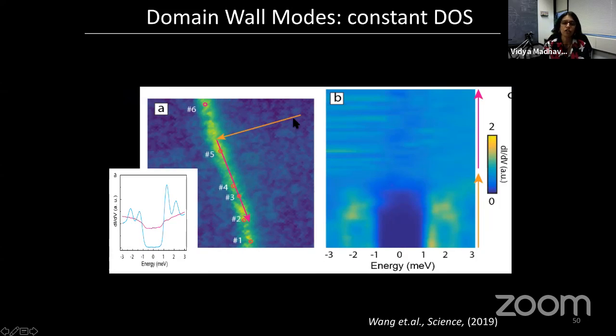You can also check this by, so here, this is an intensity map. It shows you a line cut in this direction and then in this direction. So if you follow the orange line and you take spectra along this line, you see zero density of states, that's the superconducting gap, and these are the coherence peaks. But then when you get to the domain wall and you take a line cut, you can see that inside the superconducting gap, the density of states is pretty much flat.